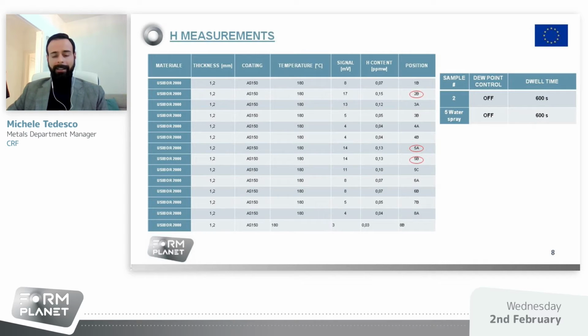Here are listed the results for all the components tested in the different conditions, and with the red circles, we can see the worst result, where we found a high value of hydrogen compared to the other ones. So the first sample is number 2, in which we set as parameter the dew point off, and we leave the blank at the maximum time in the oven.